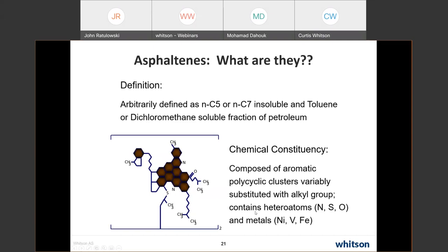They may have some heterogroups in them, nitrogen, sulfur, oxygen. The metals, nickel, vanadium, and iron, are contained within porphyrins within these structures. Now, this is just a hypothetical structure, and it actually probably has a little higher condensed aromatic area than some descriptions of asphaltenes. But asphaltenes are not as easily definable as wax. These are a large class of molecules that are aromatic and polar, whereas wax is mostly normal paraffins, some substituted normal paraffins as well. But it's easier compositionally to define a wax as opposed to an asphaltene.